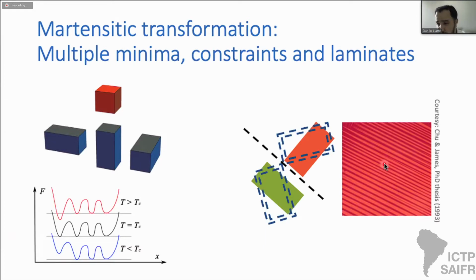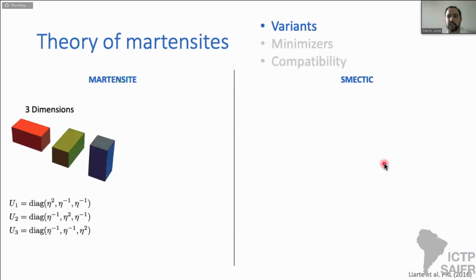Now you might be asking yourselves, what does that have to do with smectics? So in the following slides, I'm going to discuss how a generalization of the theory of Martensites gives an explanation of the smectic microstructure. There are three elements from this theory that I'm going to discuss: the variants, or low energy configurations, the symmetry of the energy minimizers, and compatibility conditions to correctly combine the different variants. I've already described the three variants in the case of a tetragonal Martensite. They correspond to deformation along the three Cartesian axes. In principle, one can assign distortion tensors to each of these configurations as shown here. You don't have to pay too much attention to those matrices. They are there just so that I can refer to them later.